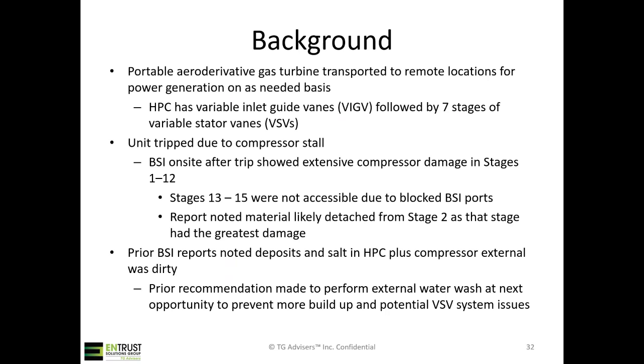Part of this RCA included evaluating prior reports just to see if there was any trends or anything to potentially warn of an impending issue. The only relevant finding from those prior borescope reports was that deposits and salt were noted in the high pressure compressor, and the compressor external was noted as being dirty in one of the reports in particular. There was a prior recommendation made to perform an external water wash at the next opportunity to prevent more buildup and potential variable stator vane system issues.